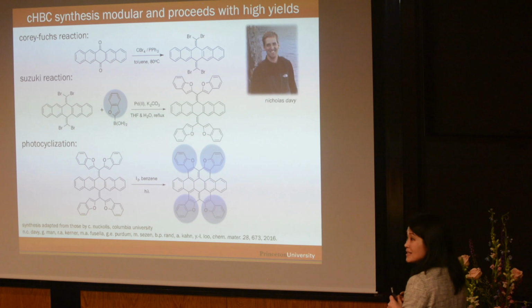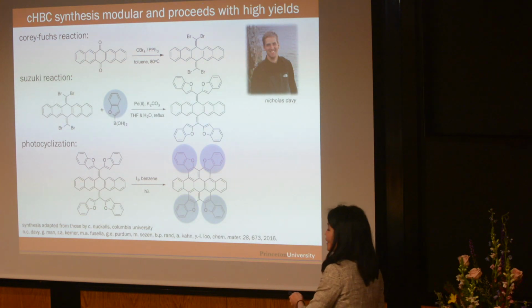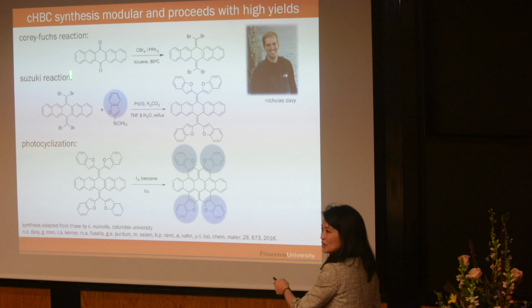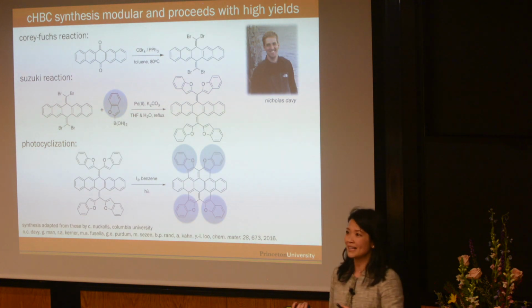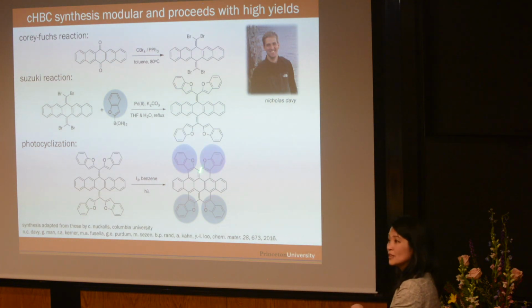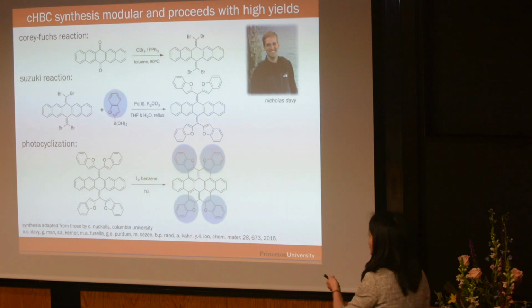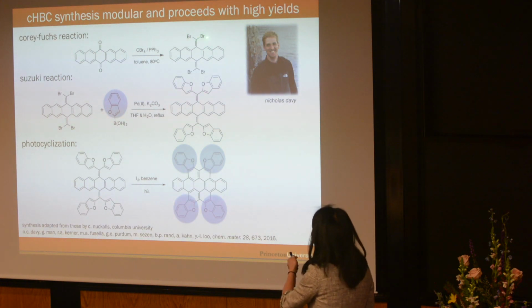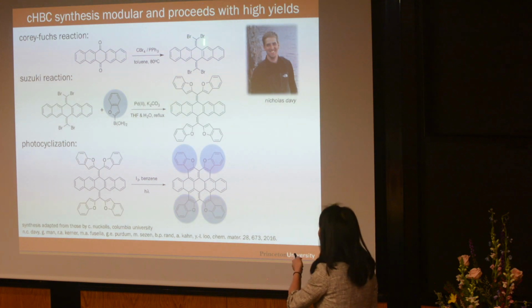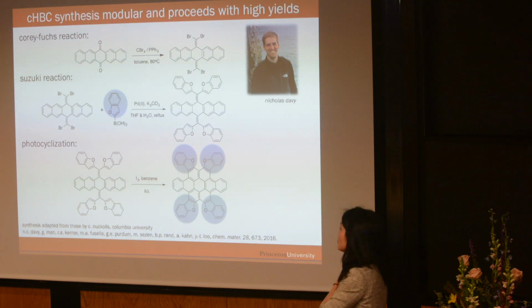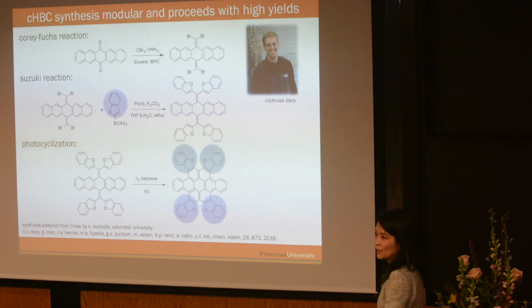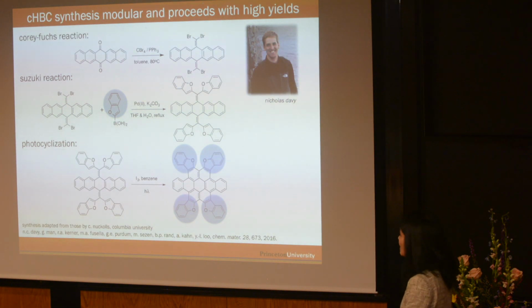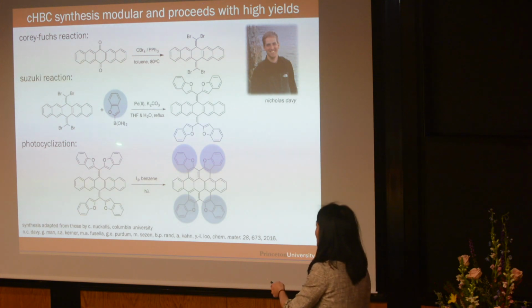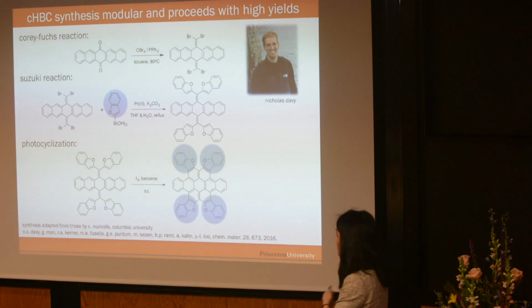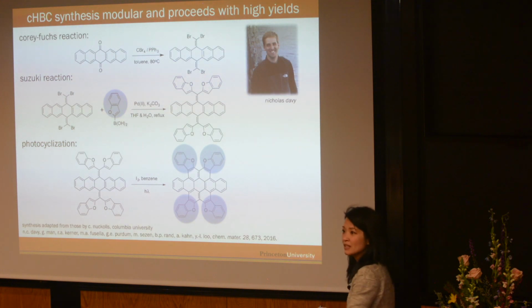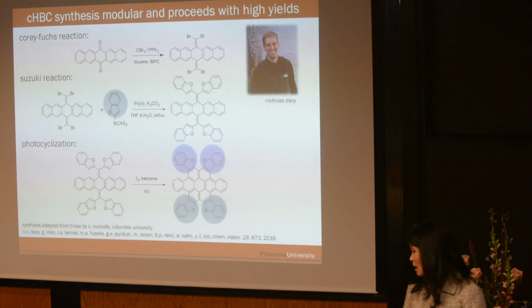We like this chemistry because it's actually super modular. In fact, if you look up Aldrich, you can buy a whole bunch of these boronic acids. And depending on what boronic acids you buy, you can make materials with different chemical functionality. Okay? You start out with a pentacene quinone, you brominate it, and then with these bromine active sites, you now add the boronic acid, and then you ring close through a photocyclization, and you get this molecule. Okay? And that's because we chose this benzofuran boronic acid. If you choose something else, it ends up here, and you can tune the optoelectronic properties of the compound.